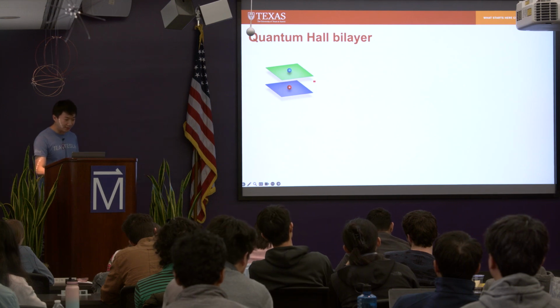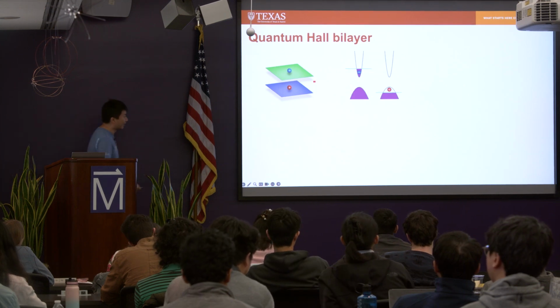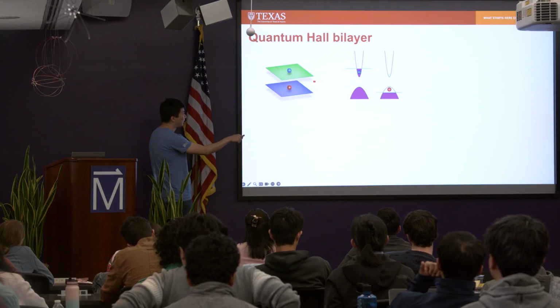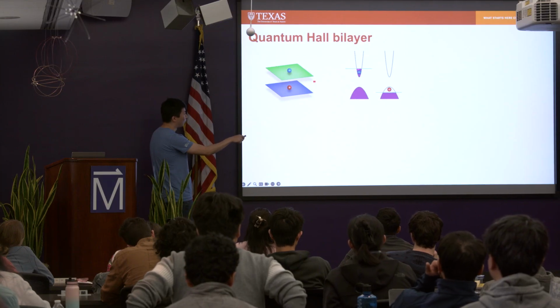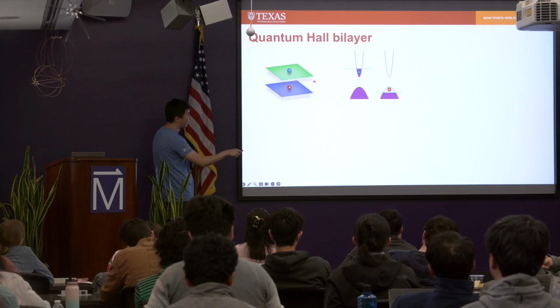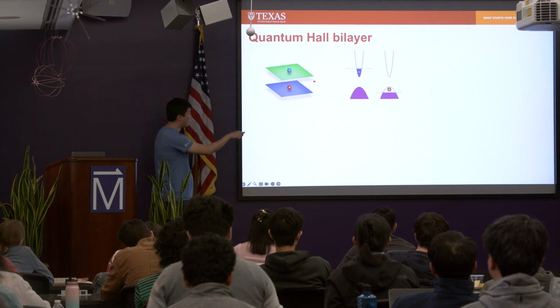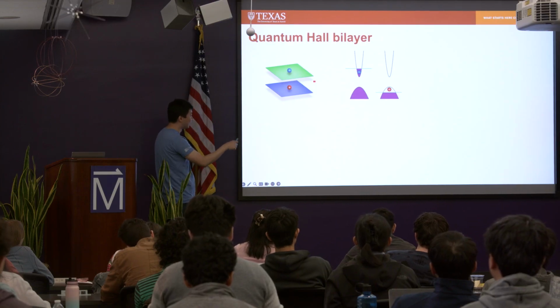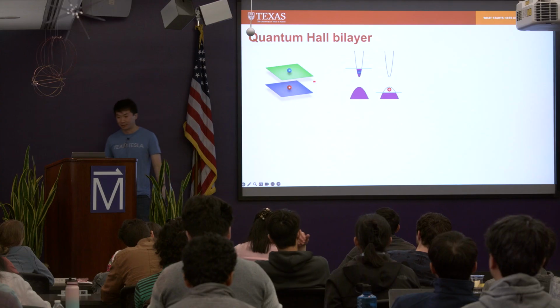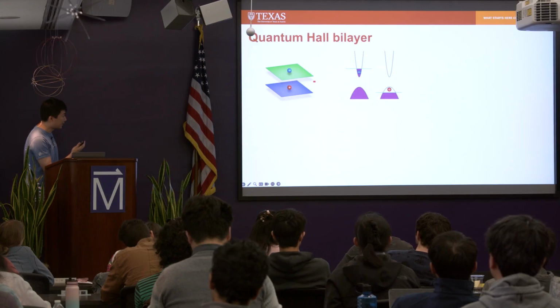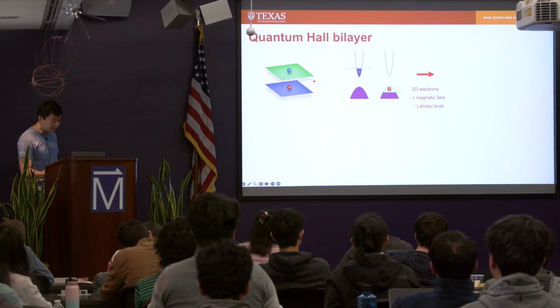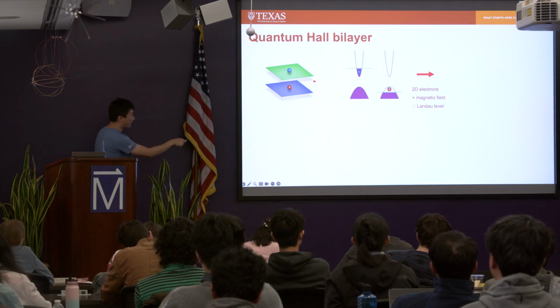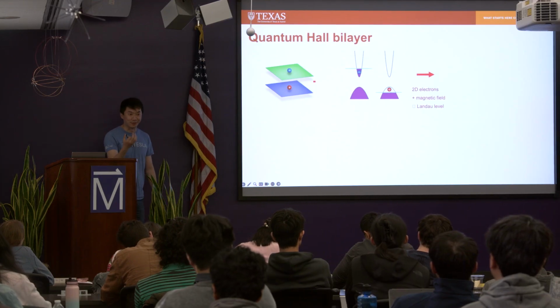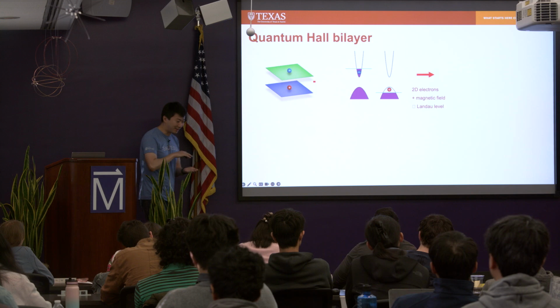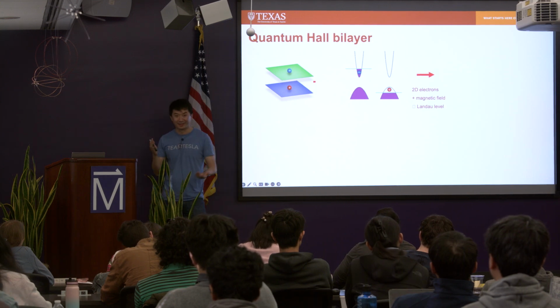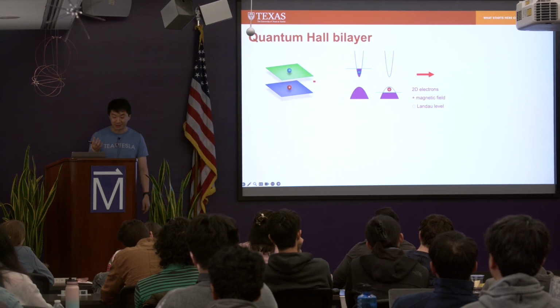And so the schematic looks like this, right? You get two of these energy bands, and you just put the Fermi energy into the conduction band in one layer and the valence band in the other layer, right? And then get them to pair, and these are spatially separated electrons and holes, right? And to address the density of states issue, right? Of course, you can just make this band extremely flat. That will require you to get two layers of exotic material, like twisted bilayers, which is doable, but right now still a challenge.